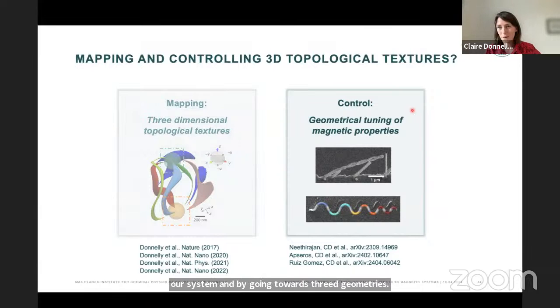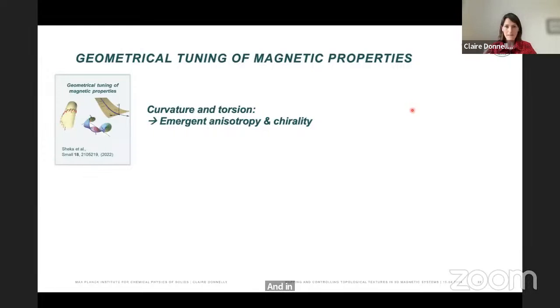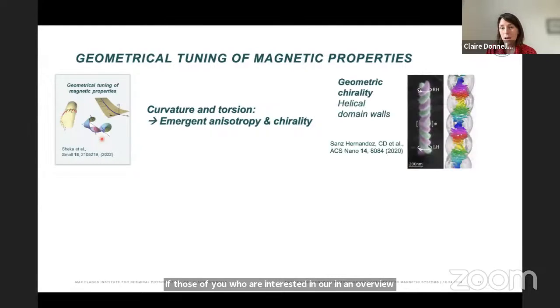In particular, the idea that we want to focus on is introducing curvature and torsion, which we can see if we take even a simple exchange Hamiltonian and transform it into a curved coordinate system: you get exchange-driven anisotropy and chirality terms popping out. So by introducing curvature, introducing symmetry breaking, you can start to tune the interactions of your system. Now, there's already been quite a lot of work done to this extent. For those of you who are interested in an overview of this, I would very much recommend Denis Sheka's review paper here. But in the last few years we have also started to explore this direction experimentally.